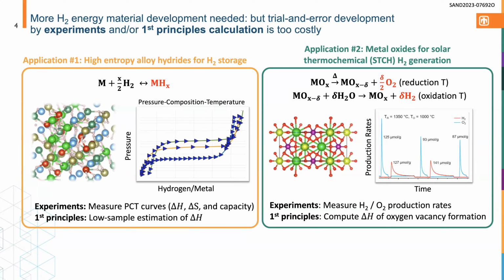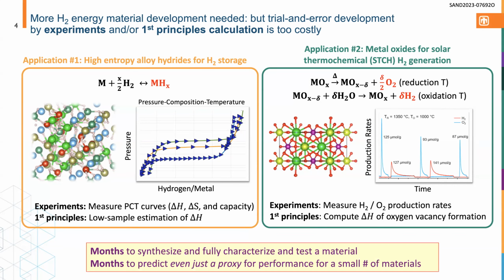enthalpy. The second application is solar thermochemical hydrogen generation, where we basically reduce and oxidize a metal oxide at really high temperatures to produce hydrogen. Experimentally, of course, we can do this. First principles, we definitely don't predict these production rates as a function of time. You see here, the best we typically do is compute delta H of the oxygen vacancy formation energies. So the ultimate problem is that it takes, next click, is that it takes months to make these materials. It also takes months to just predict a proxy of performance for a small number of materials.